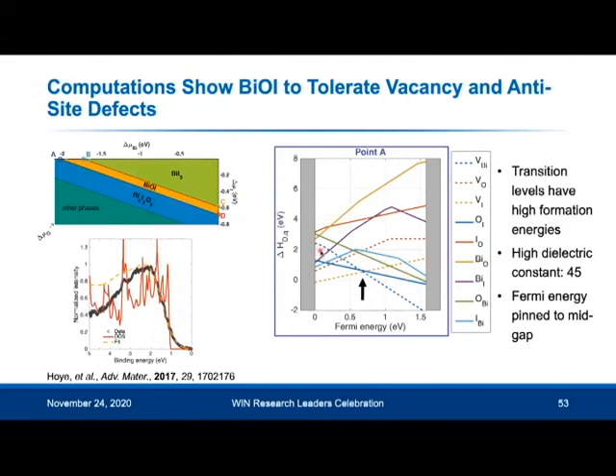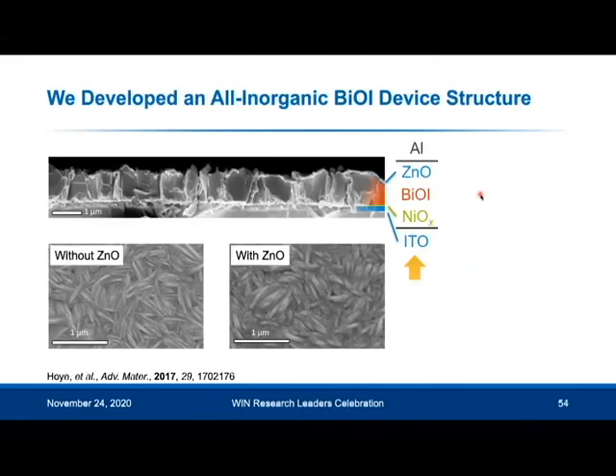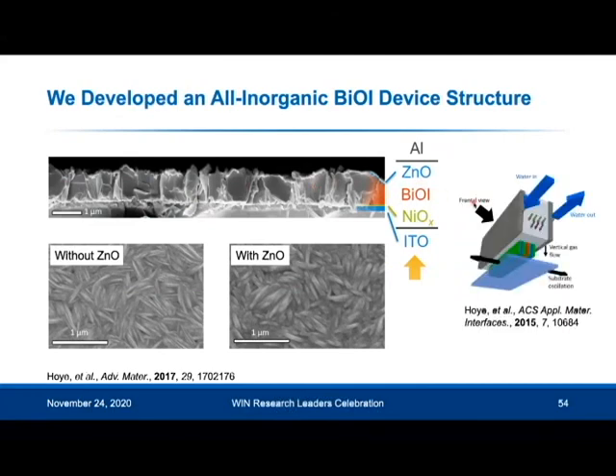And this agrees with our hypothesis that the defects will be either resonant within the bands or shallow within the band gap. And this shows that this material tolerates these vacancy and anti-site defects that we considered. So we next made these into devices, and one of the challenges is that the BiOI is very heavily textured. So we can't just spin coat the zinc oxide electron transport layer on top. But what I can use is the APCVD reactor I was talking about earlier to grow the zinc oxide conformally onto the textured BiOI.